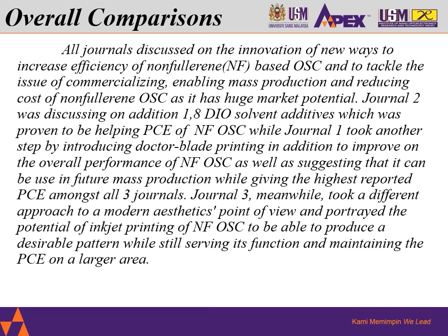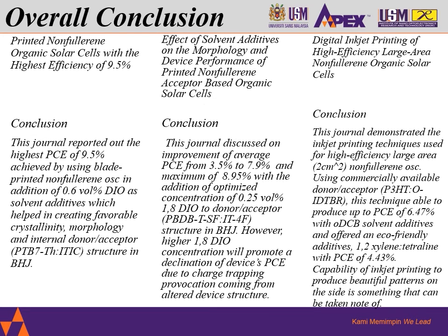And then journal number 3, meanwhile, took a different approach, from a modern aesthetic point of view, and portrayed the potential of inkjet printing to produce a desirable pattern while still serving its function and maintaining the PCE on larger area. As the overall conclusion for all 3 journals, the first journal concludes that the highest PCE of 9.5% was achieved by using blade printing non-fullerene organic solar cells, in addition of 0.6 volume percentage of DIO solvent additives, which help in creating favorable crystallinity, morphology, and internal donor acceptor structure in the blend heterojunction.